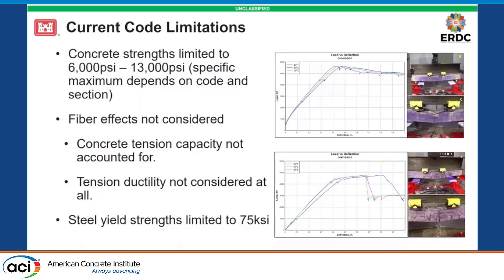So if you're looking at the upper, that is a fiber reinforced specimen with no shear stirrups, and the bottom is a non-fiber reinforced specimen with shear stirrups. You can see the significant change in the ductility, or rather the deflection, which is an indicator of the ductility between these two test specimens. So clearly our existing codes don't capture any of that additional ductility, and in fact would argue that the top should be significantly less ductile than the bottom.